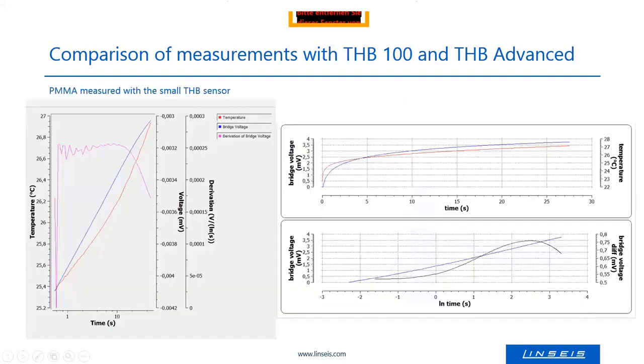So the first measurement was done with PMMA. So this can look familiar to those who have an equipment. You see the bridge voltage, blue line. The pink line, it's the first derivative of the blue line, and the red line is the temperature increase. And from these data, you can calculate the thermal conductivity and thermal diffusivity.